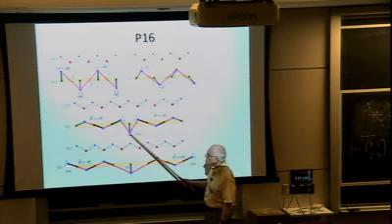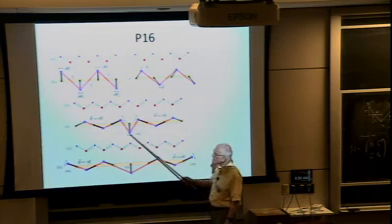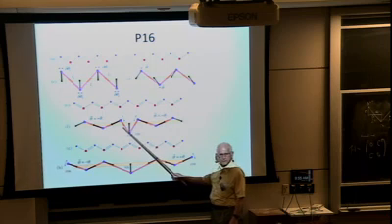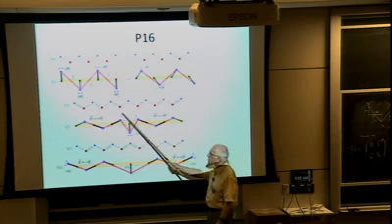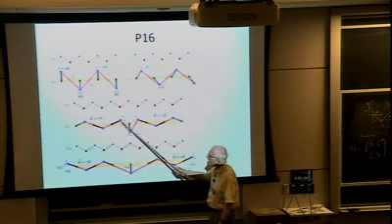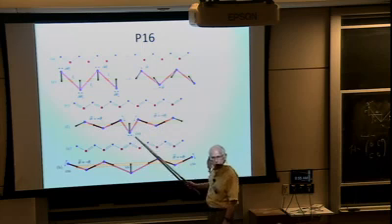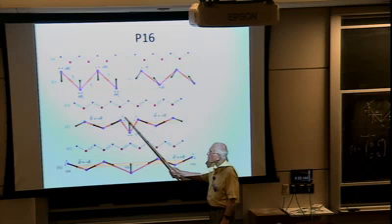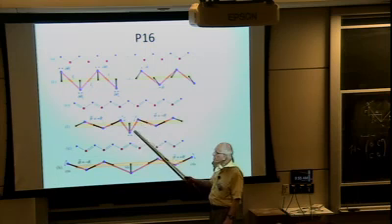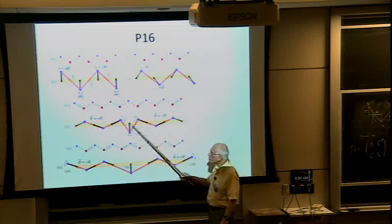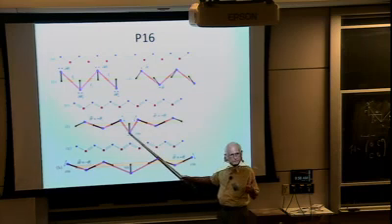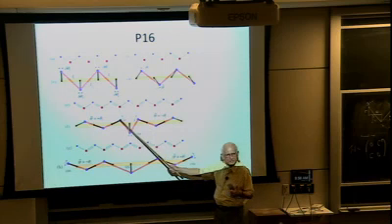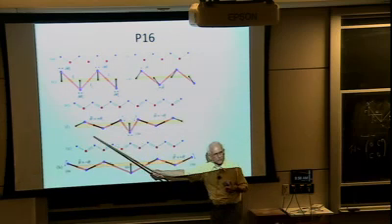Now here's one way of doing it. I connect it together by adding one site and two bonds. To ask whether or not we have a 0 mode here, we look at this collection right here and ask, for this grouping, what is the compatibility matrix associated with this. So there we have one bond, one site, and two bonds. This site has 1 degree of freedom, and I have 1 degree of freedom, which is the amplitude of the decaying mode in that direction.